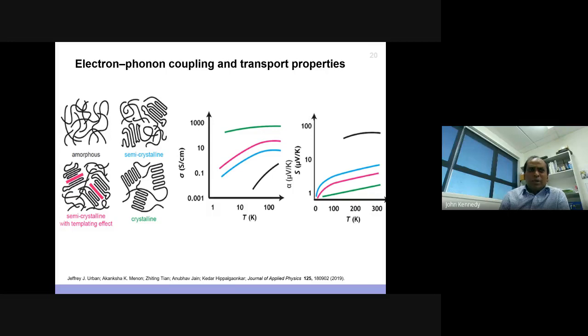And as I said, the phonon coupling is one of the things which is heavily studied. You can see in the organic materials, the electron-phonon coupling, to the extent where it is spatially and energetically disordered in organic materials and hybrid materials, it's amorphous or semi-crystalline. If you look at the temperature dependence of sigma and Seebeck, it's going up, and at some point it's going up in some cases as well. When it's amorphous materials, it keeps on going up. So that gives you a rough idea. All right, so this actually came from machine learning, applying AI to predict what are the ways it can go. This publication came recently from one of my collaborators' groups.